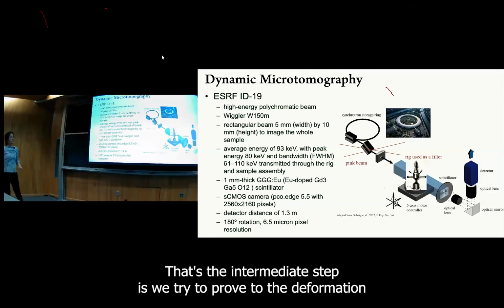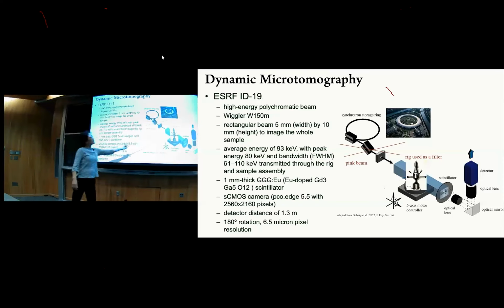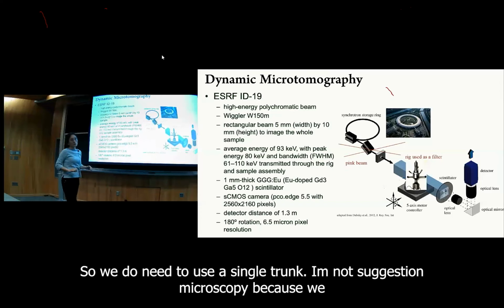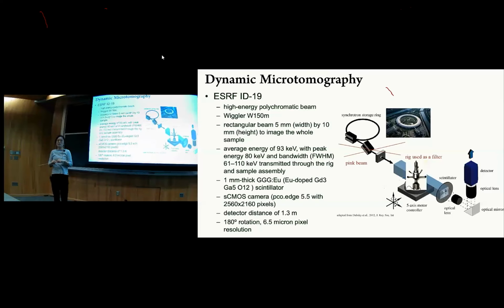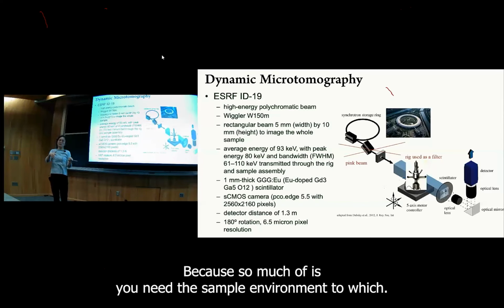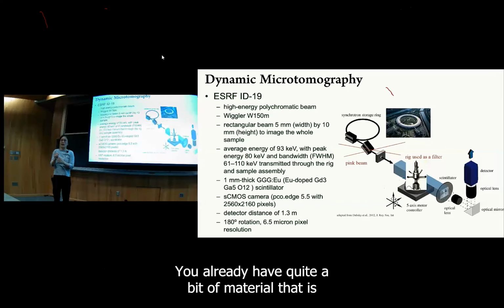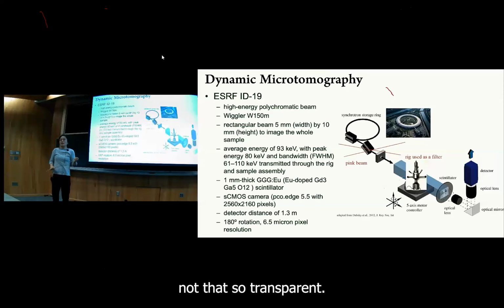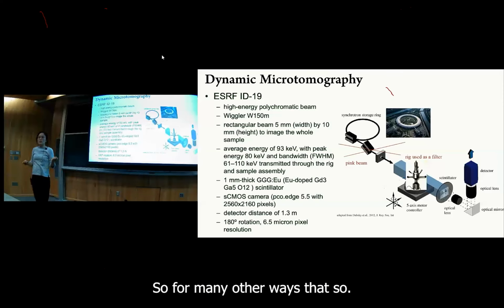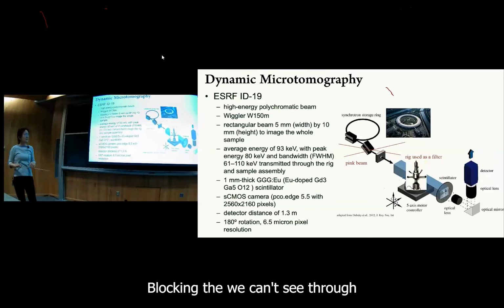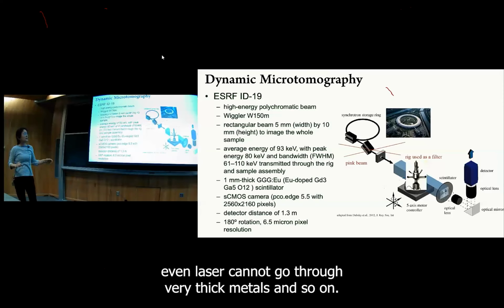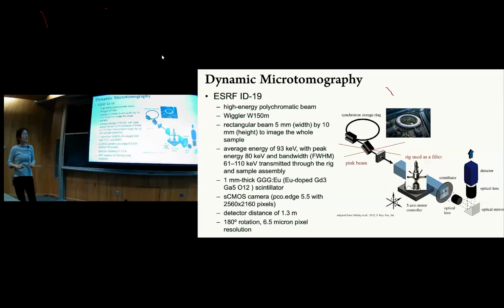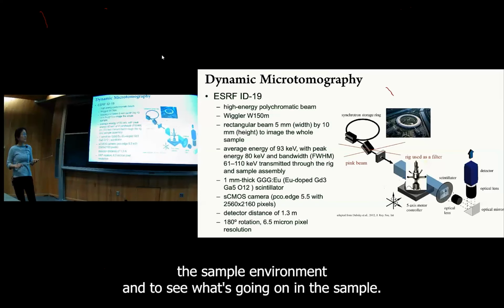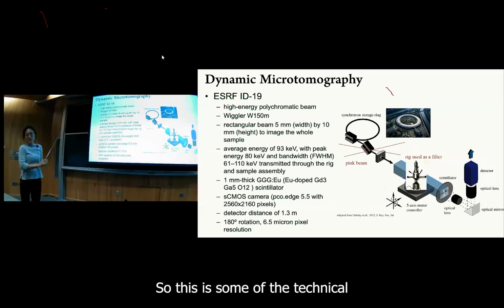And how do we do that? The intermediate step is we try to put the deformation rig, here is one of them, into the synchrotron beamlines. We do need to use a synchrotron, not just a micro CT, because we need more energy, more flux. You need a sample environment to build the pressure and temperature, so you already have quite a bit of material that is not that transparent to many other methods. It's blocking, we can't see through, even laser cannot go through very thick metals. So X-ray becomes one of the means that you can go through the sample environment and see what's going on in the sample.